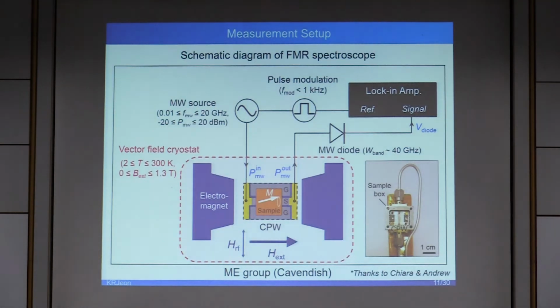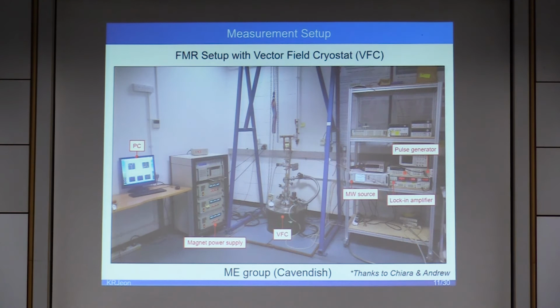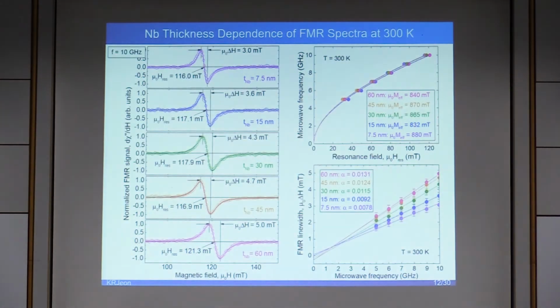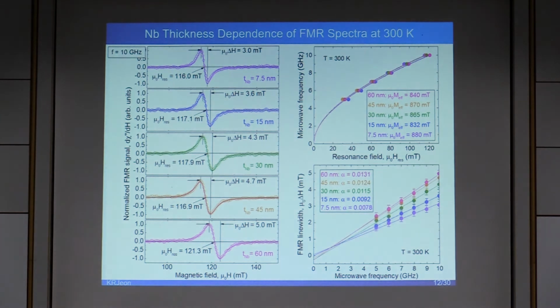We first confirmed dynamic exchange coupling between permalloy and niobium layers of the sample by measuring FMR spectra as a function of niobium thickness using a broadband FMR setup, which involves a microwave source, lock-in amplifier and coplanar waveguide at the microelectronics group at Cavendish Laboratory. This figure shows typical FMR spectra obtained from the sample without the platinum layer at the fixed microwave frequency of 10 GHz at room temperature.